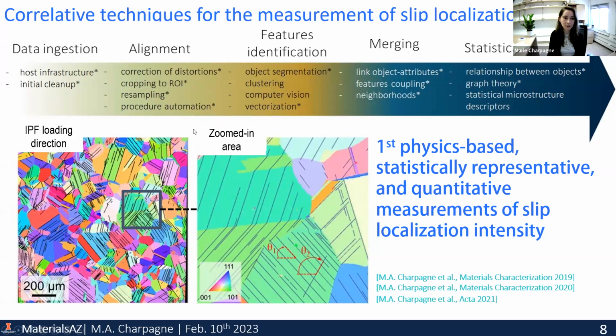And over the past 2 to 3 years, I've developed some data merging capabilities and correlative microscopy tools so that we can accurately recombine these very high resolution digital image correlation maps with EBSD. The challenge is essentially that you collect these two with different detectors, at different tilt angles, with different beam settings and acceleration voltages, and EBSD is really subject to a lot of distortions. So it's not something you can just eyeball and do by hand, especially when you collect areas that are of millimeter size. And so with machine learning and image segmentation tools, I was able to come up with a framework that takes DIC images on one hand and EBSD data on the other hand to recombine the location of each slip band into the initial microstructure.